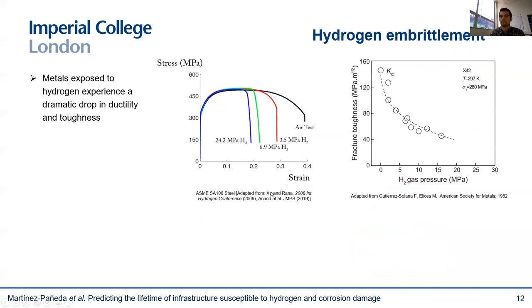So let me start with the modeling of hydrogen embrittlement, which is becoming notoriously important. The issue is that hydrogen is a virus for metals. Metallic materials exposed to hydrogen experience a very significant reduction in ductility and fracture toughness. If we increase the content of hydrogen coming into our metallic samples, we will observe a very noticeable drop in the failure strain. And the same goes for toughness. In fact, the reduction in fracture toughness can be of up to 90% for some alloys.